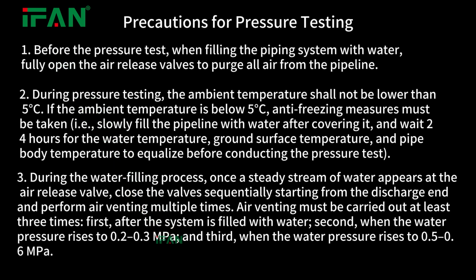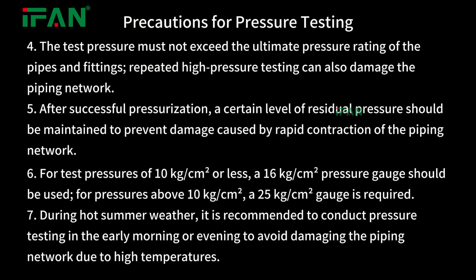3. During the water filling process, once a steady stream of water appears at the air release valve, close the valves sequentially starting from the discharge end and perform air venting multiple times. Air venting must be carried out at least 3 times. First, after the system is filled with water. Second, when the water pressure rises to 0.2-0.3 MPa. And third, when the water pressure rises to 0.5-0.6 MPa. 4. The test pressure must not exceed the ultimate pressure rating of the pipes and fittings.